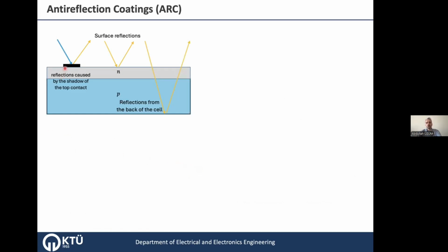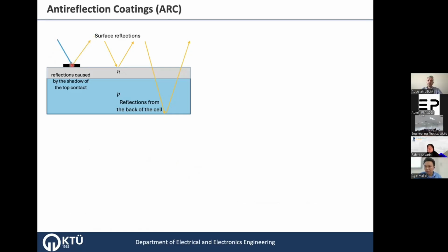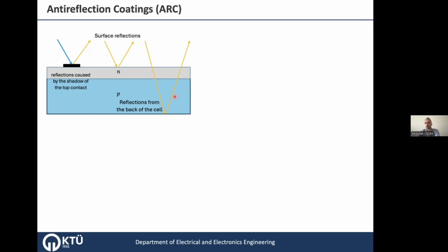As you can imagine, we have losses, optical losses and electrical losses, as I said. To reduce the optical losses on the surface, the reflection losses, we can say, because we have contacts on the front surface, incoming light can reflect from these contacts, and these are losses that you cannot do anything about because it will reflect from the contact surface. But what we try to do is to reduce the illuminated surface reflections, like this one. And also there are some losses caused by reflection on the back surface. And you will see that the PERC design and the TOPCon design that we will be talking about actually help to reduce these kinds of reflections too.